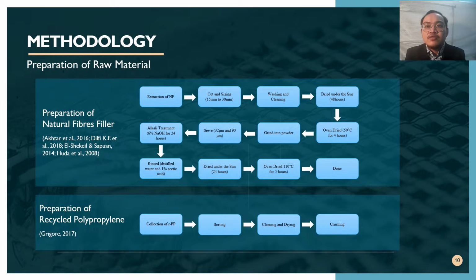For the next step, the fiber is put into a high-speed blender machine to grind into powder form. Afterward, it is sifted using a sieve shaker machine for 20 minutes to separate it into sizes of 32 and 90 micrometer. After that, the fiber powder is treated with chemical treatment, which in this study uses 6% sodium hydroxide solution for 24 hours. Later, the fiber will be rinsed with distilled water with 1% of acetic acid until the pH level turns neutral. For the final step, the rinsed powder will be left under the sun to dry for 24 hours and continue with oven drying at a temperature of 110 degrees Celsius for 5 hours.